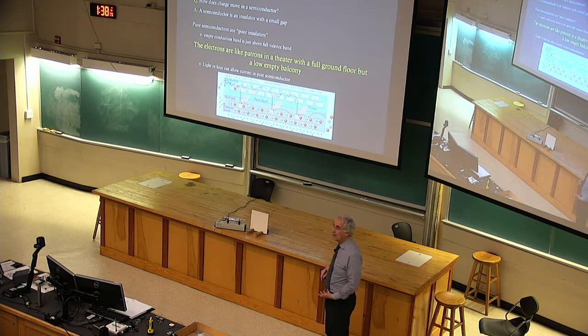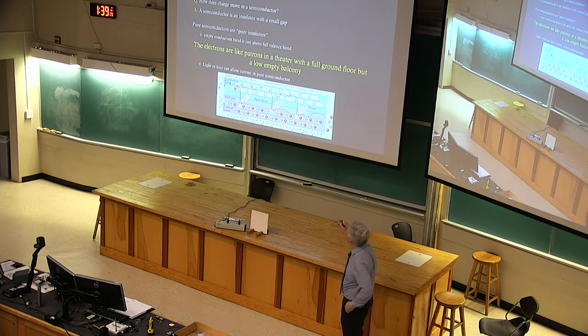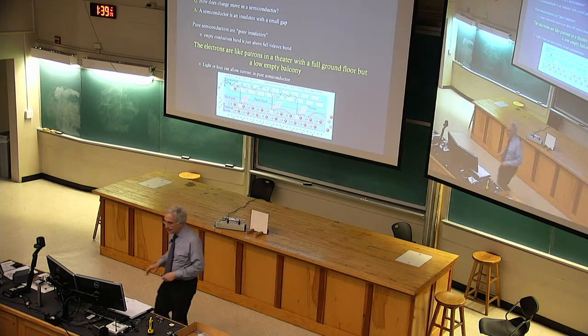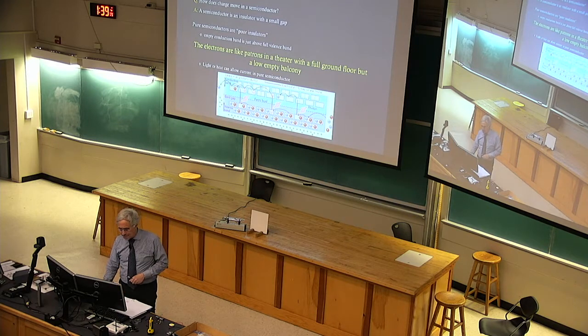They apply a coating on that drum that is an insulator in the dark and in the cold, because all the electrons have piled into the valence band and below and filled it, and the conduction band is empty. But you expose it to light, and now the electrons can move from valence levels to conduction levels, and now they can move. Questions? That's back to the xerographic copier. So light can turn these materials into conductors. All right.